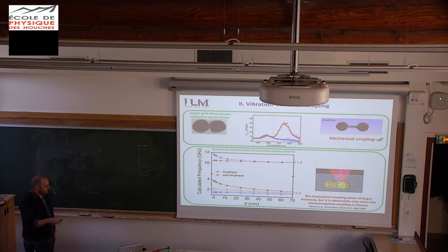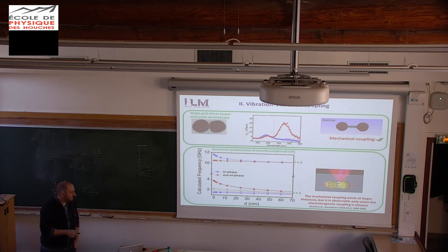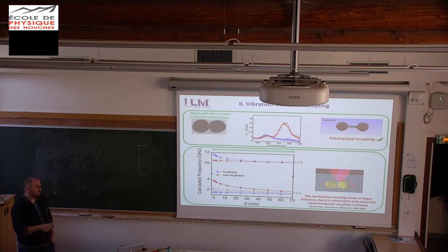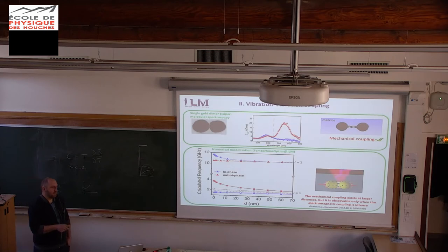But what is interesting here is that for half the diameter of the nanoparticles, we should still observe acoustic hybridization. But nobody has observed it, and many people have worked on gold nanoparticles inside glass samples where nanoparticles were close enough to observe this. But the point is that to observe this hybridization, you need a plasmon. Because this is what you are detecting when you are doing Raman, it's the modulation of the plasmon in between the two nanoparticles. This gives you the polarizability, and this is what you are detecting. So you need the plasmon to detect such an effect. So we are quite lucky on that.